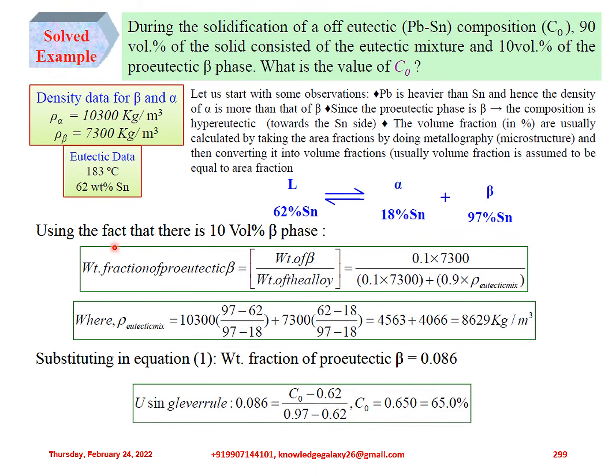and the reverse reaction takes place on heating. Using the fact that there is 10 volume percent of beta phase, the weight fraction of pro-eutectic beta is equal to weight of beta divided by weight of the alloy. Putting the values, it gives 0.1 times 7300 divided by 0.1 times 7300 plus 0.9 times rho eutectic mix. Where rho eutectic mix is equal to 10,300 times (97 minus 62) divided by (97 minus 18) plus 7,300 times (62 minus 18) divided by (97 minus 18), which is equal to 4563 plus 4066, equal to 8629 kg per cubic meter. So now substituting in equation 1, the weight fraction of pro-eutectic beta comes to 0.086.